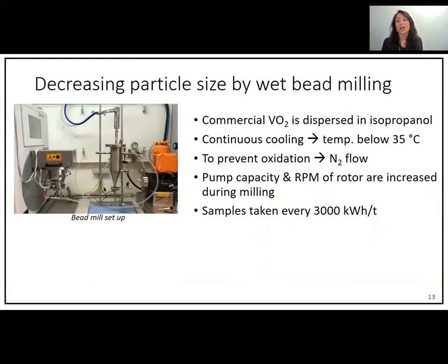Moving on to the second challenge previously mentioned, the particle size is decreased through wet bead milling of commercial VO2. The VO2 is dispersed in isopropanol with a weight content of 10 weight percent in order to have enough interactions with the beads within the chamber. Cooling water is required to make sure the temperature remains below 35 degrees to avoid evaporation of isopropanol and also to avoid oxidation of vanadium dioxide. Nitrogen flow is applied in the mixing tank.